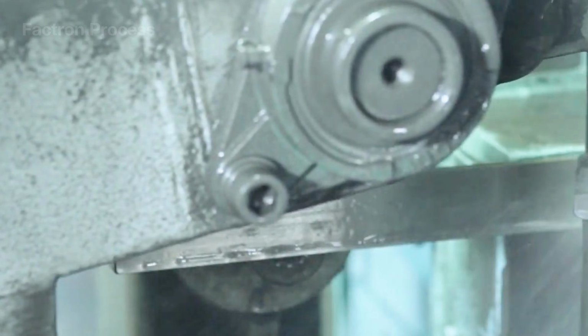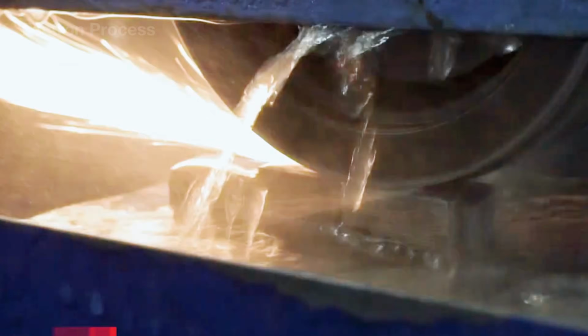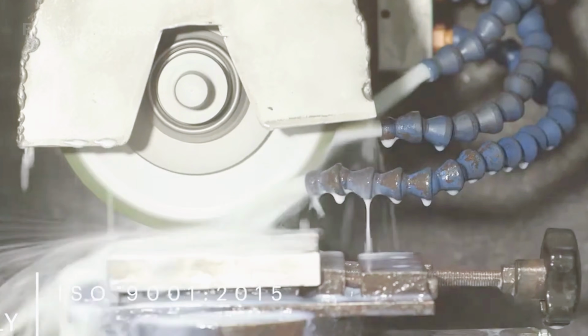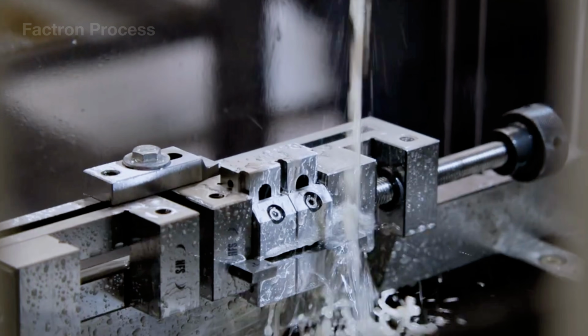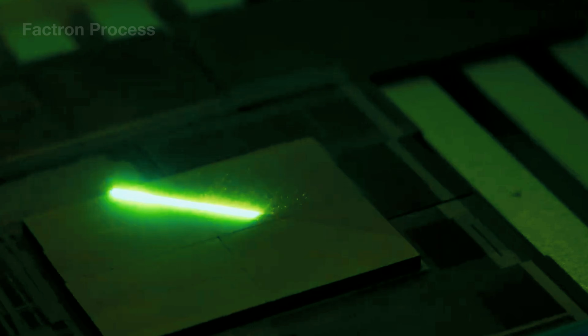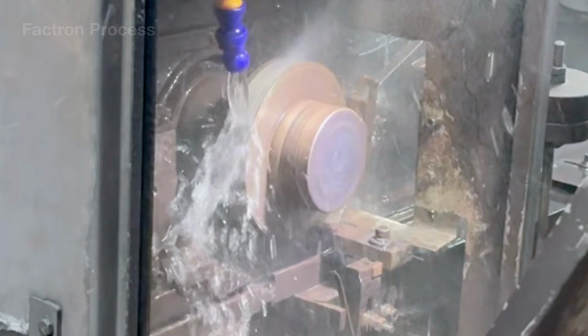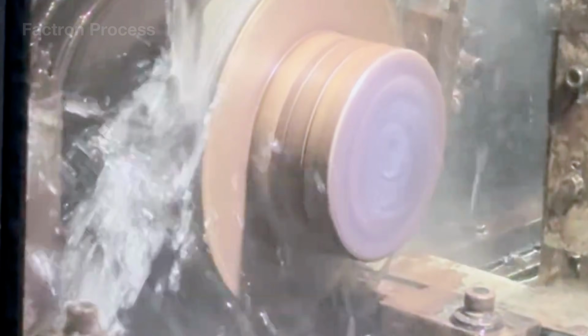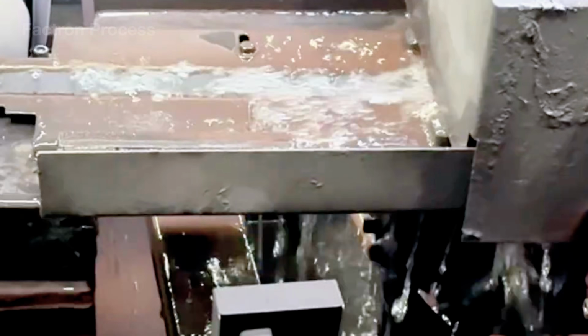After sintering, the compact is extremely hard but brittle, so it is sliced into thin plates using high-speed diamond wire. The plates are then cut, drilled, or ground into discs, rings, rectangular blocks, or curved motor segments, with tolerances below 0.01 millimeters. Coolant is sprayed continuously to control heat and reduce the risk of NdFeB dust ignition.